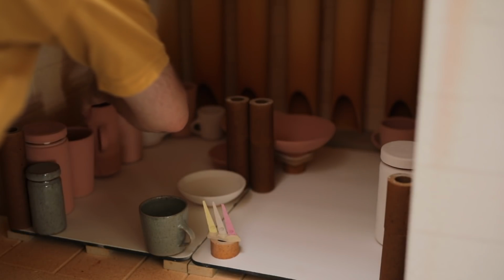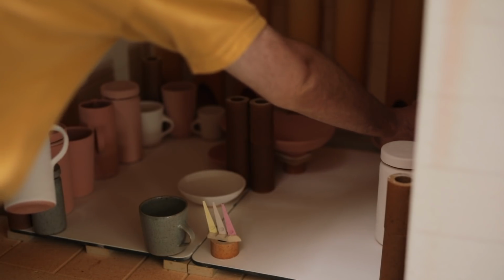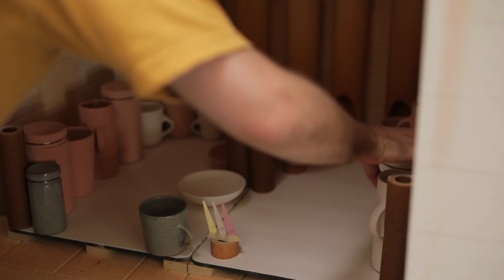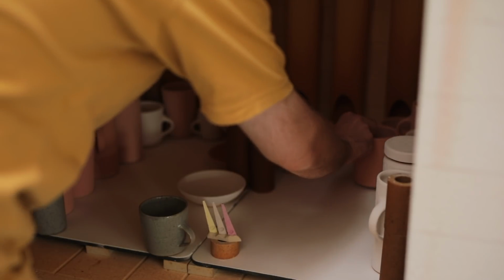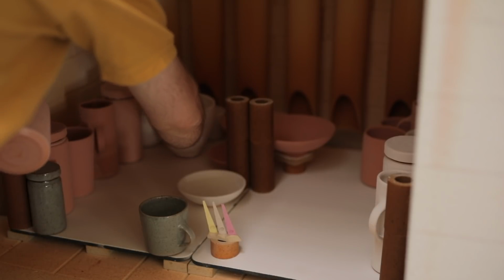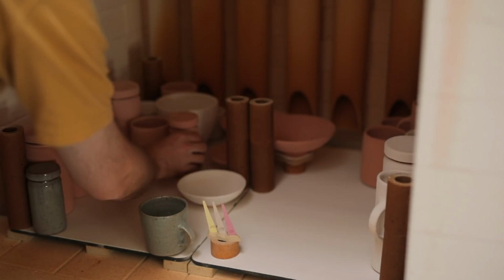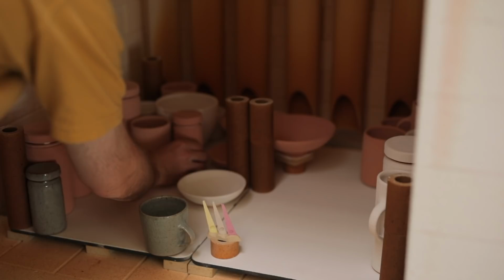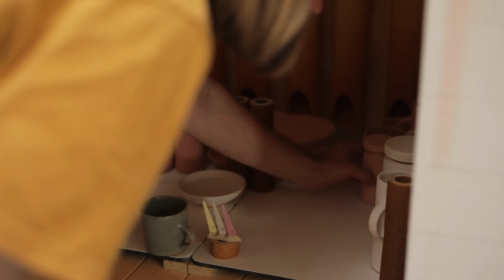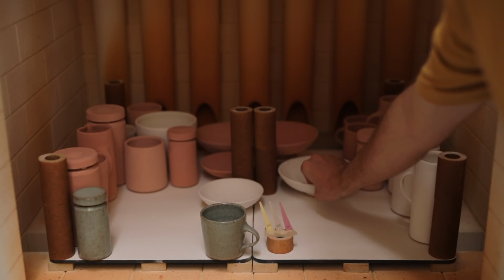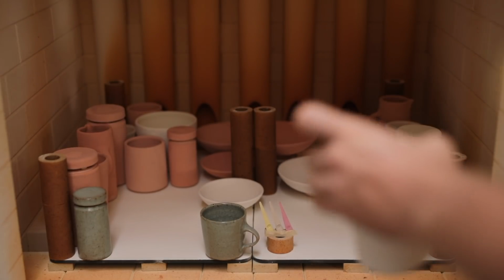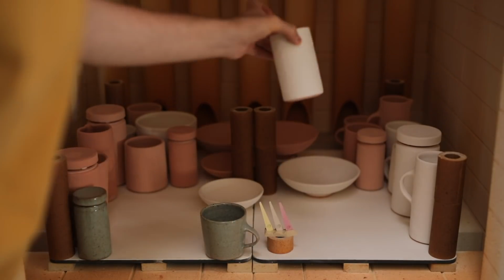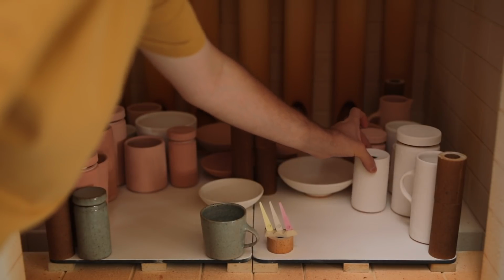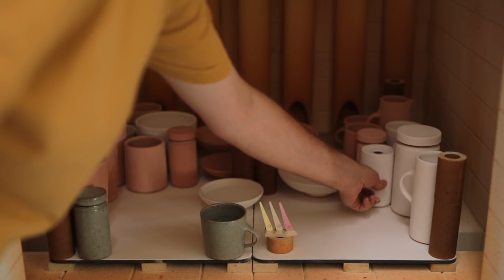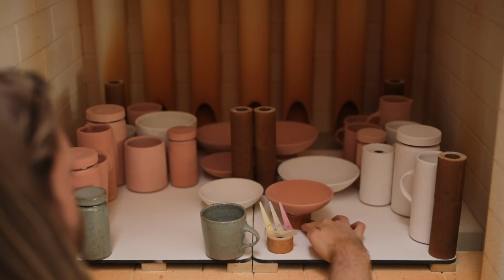If they do touch, what happens is that during the firing, as the glaze melts, the pots simply fuse together, which isn't ideal. But there is a rule for packing this lowest shelf that doesn't apply to any of the other layers, which is followed to try and get as even a firing temperature-wise as possible, and you can kind of see it here. On the lowest level, I place taller pots on the left and right side, and as they get towards the centre, they get lower and lower, essentially creating a cavity into which the flames will be able to flow more easily.